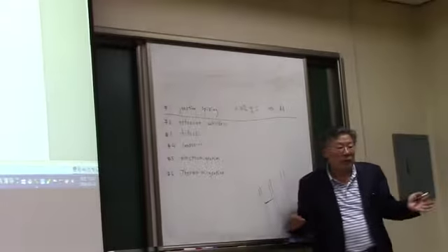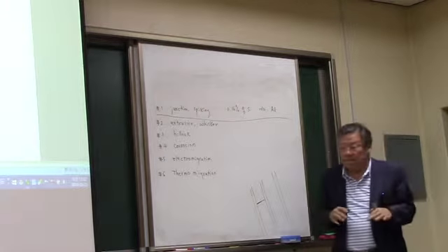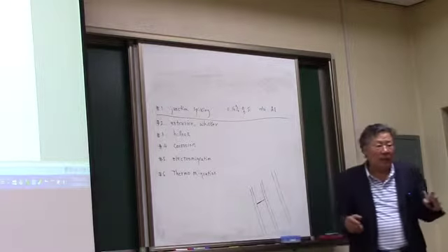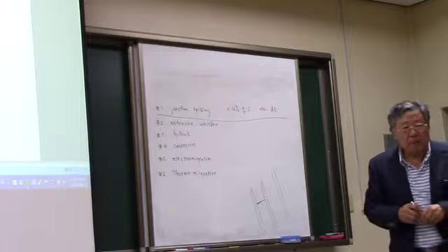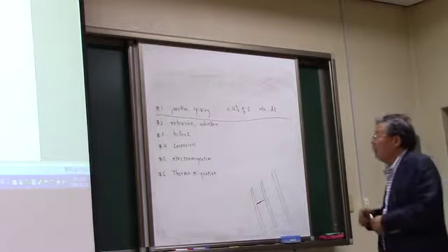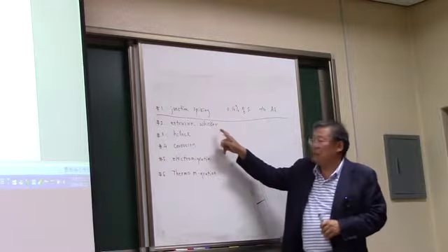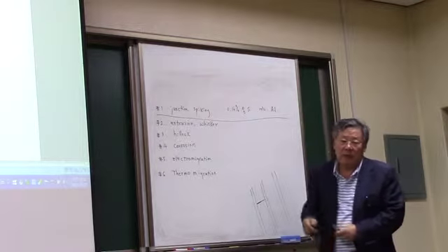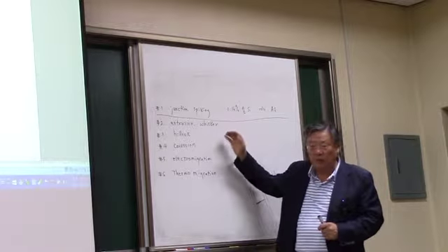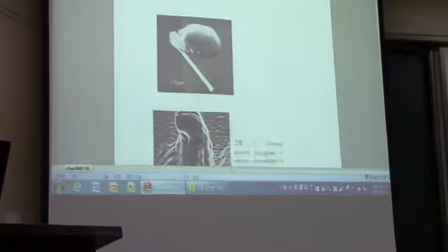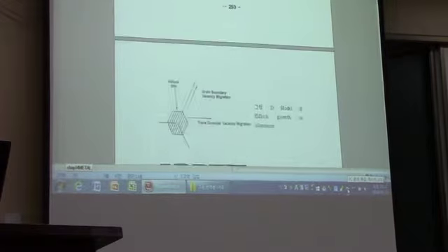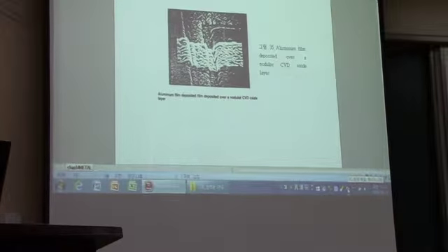And with extrusions, we are going to have a rough surface, and that rough surface is a big problem in lithography. In lithography, we are going to have very fine patterns. So extrusion and whisker come from the mechanical stress, and it's not a trivial question at all. We have to prevent this. Now, how can you prevent that? We are going to add the vacancy sink. Where is the vacancy sink?